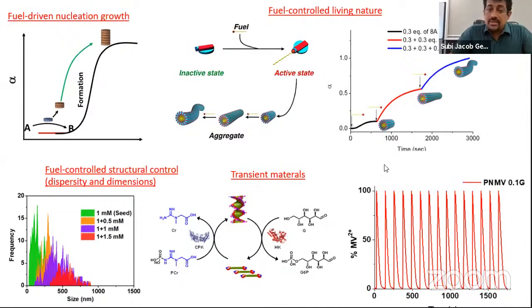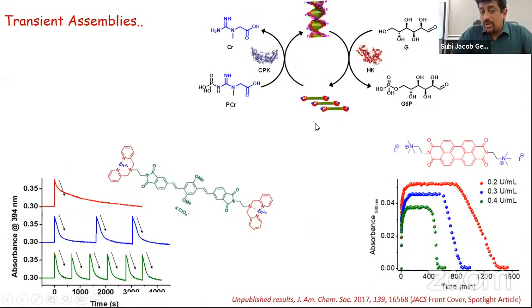So what I want to say is, by this process, we have a structural control, and then we can make transient assemblies. So you see that just by changing the concentration of this enzyme, we can tell how much time this polymer should be stable. So in this case, it's stable for a few minutes. You change the enzyme concentrations, you can change the lifetime of the material. So the transient materials are those materials where you can pre-program the lifetime. Okay, so we believe these are the disadvantages one could address by going into biomimetic designs.